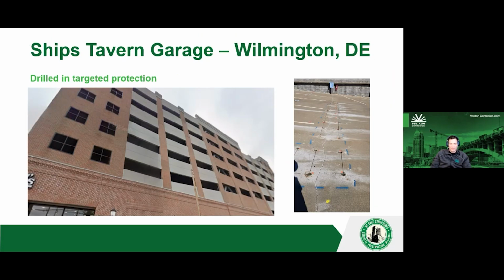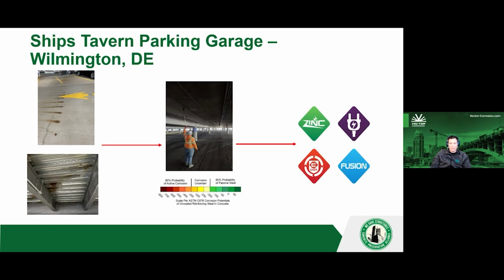Next thing I want to talk about, Ship's Tavern Garage in Wilmington, Delaware. This was a situation where they used drilled-in targeted protection. Something unique about this structure is that it has some welded wire rebar on top. We have some studs connecting it to a galvanized pan decking. This galvanized pan decking provided structural capacity, and you can see there's corrosion activity going on the bottom, which is not good, especially if it's providing structural support. And think about the amount of corrosion activity going on to eat through the galvanizing and then also show signs on the bottom of the structure.